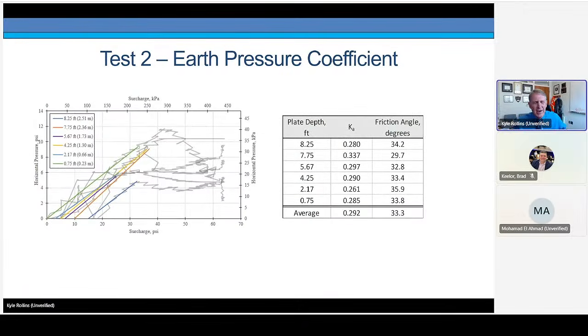We can take all the pressure cells. They have some offsets to begin with, but if we just plot kind of the best fit of the lines of horizontal pressure relative to surcharge pressure, we can get a first estimate of K sub A. And for those different depths, you can see the variation. The average is 0.29, so it's not far off of what we were seeing. We've back calculated the friction angle for each of those, and on average, it would be around 33 degrees. So that's not too far out of line with the 34 degrees we've been looking at.